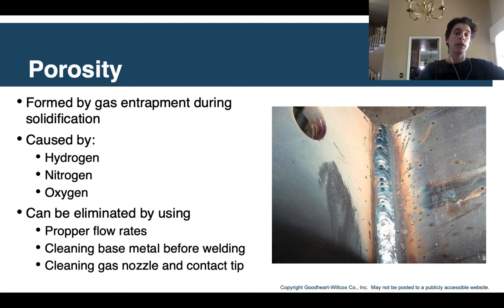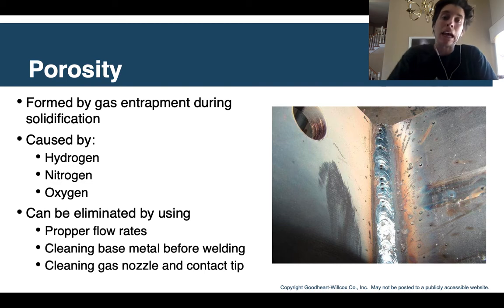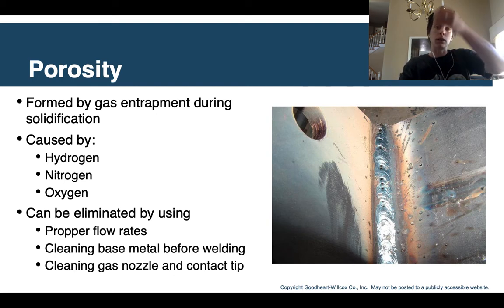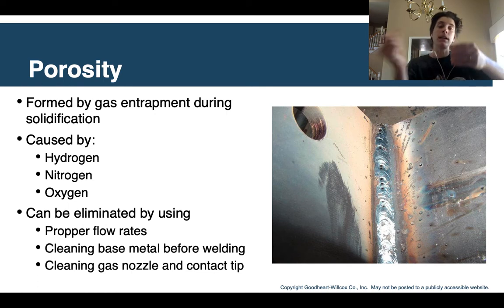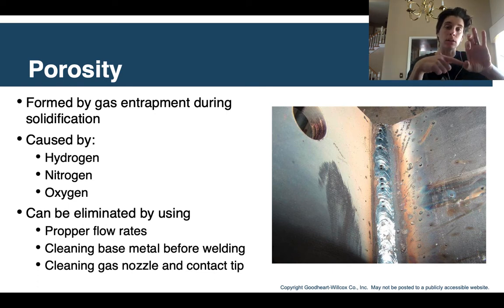Another very important thing to check is the gas nozzle and contact tip. This is where those MIG welding pliers are going to come in really handy. The gas nozzle is this kind of cone shape. The contact tip fits inside of it. The gas nozzle is going to collect a lot of spatter around the inside, and as you're welding, it just builds up in there. So you're going to want to occasionally clean that out. That really does affect your weld.